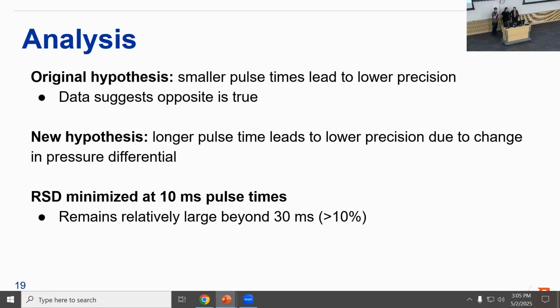All right, so regarding that initial hypothesis that the smaller pulse times would lead to lower precision, the data actually showed that the opposite was true. These smaller pulse times had the best precision. We looked at the data for a while and came up with a new hypothesis that the reason the longer pulse times didn't have good precision was due to a change in pressure differential during the dosing. The cross chamber and the main chamber have different pressures, and there's a differential between them. This is what causes the gas to flow in the first place.